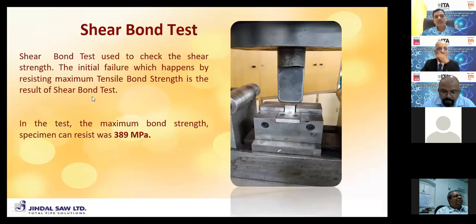Next slide, please. So yes, there is a very important test, that is the shear bond test. We have to conduct the shear bond test between the CRA and the base metal. So we conducted the shear bond test and found that it is well within the standard range.